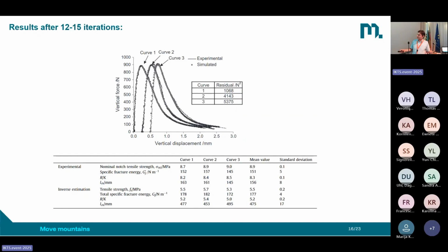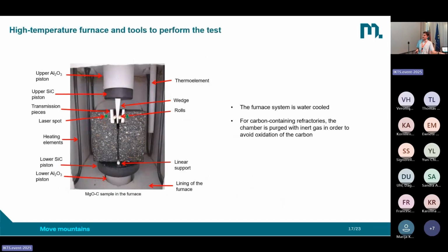What does it mean now for the characteristic length if we have these two different parameter sets? If we take the parameters from the experiment, we are getting 163 millimeters, and from the inverse evaluation, we are getting 477. So it's completely different. So these have been room temperature experiments and evaluations.